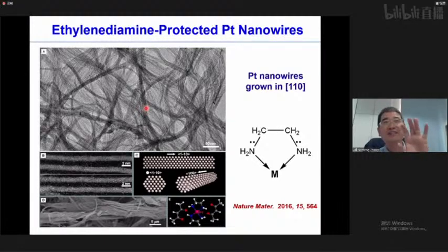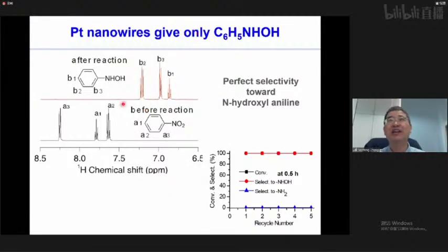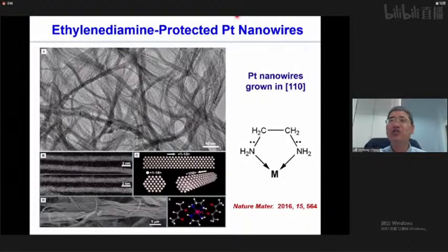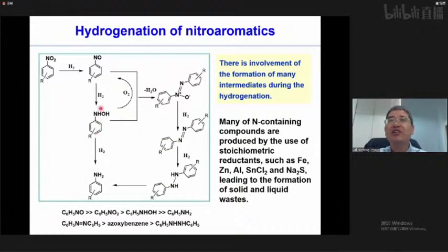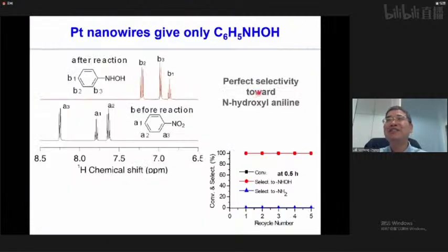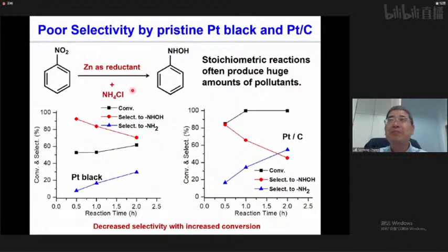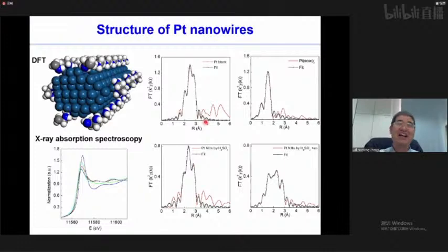So this nanowire is quite unique in the hydrogenation of nitroaromatics. We only get this hydroxyaniline. This is quite unusual because the further hydrogenation of hydroxyaniline to aniline is so thermodynamically favorable. Why do we only get this hydroxyaniline? Okay, so you see, they can be recycled many times. If we use unmodified Pt catalyst, we always see a decrease in selectivity with the increase of the activity and the conversion. So why are these nanowires so unique?